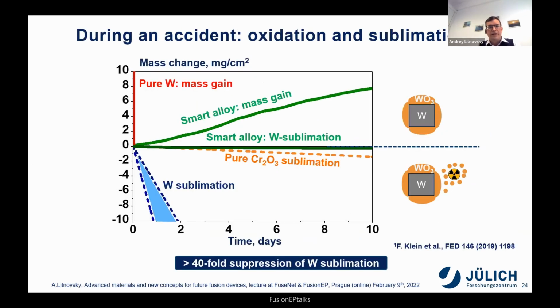To see how this material works, it is actually shown here in numbers. So it is a mass change in the course of oxidation, in the course of the contact in the humid atmosphere at 1000 degrees C. One can see the pure tungsten. In fact, as this graph goes up to 10, it's really rockets. The mass gain because of oxidation, so the material becomes thicker, of the smart alloy is very, very benign. But it is not oxidation which makes the problem. The material just becomes thicker, loses the shape, and so on. It is the subsequent sublimation which leads to the radioactive release.